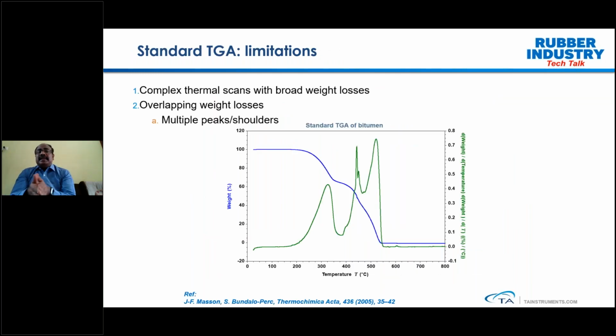Now let's talk about the limitations of standard TGA, and then we can talk about the advanced mode that can be a solution for dealing with this kind of complicated situation. Many times, if you look at the standard TGA, you may see a complex thermal scan with broad weight losses, like what you see here. And many times you see overlapping weight losses with multiple peaks and shoulders. Like you can see here, the sample is showing a multiple decomposition pattern,